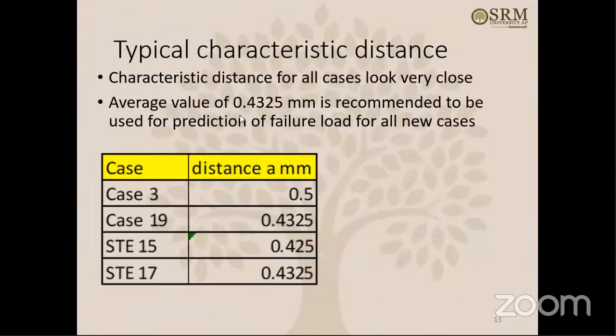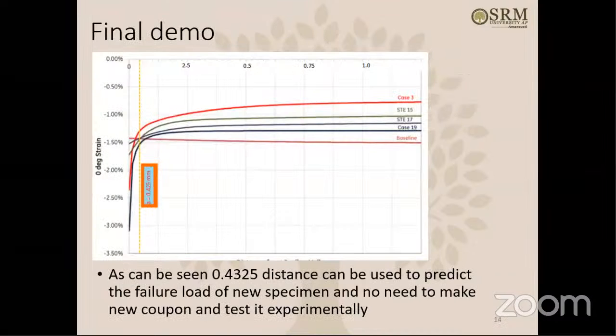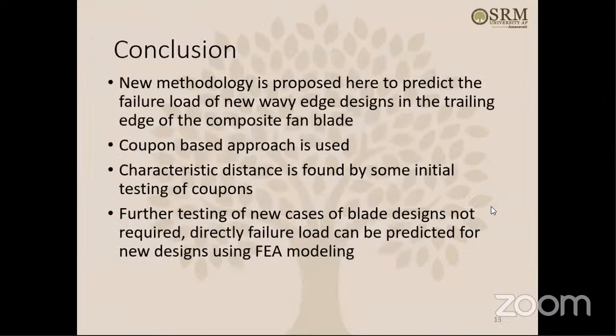Once we find this characteristic distance at which the strain variation meets the baseline level, that can be used to predict the failure load for new cases like this. As you can see, the 0.4325 distance can be used to predict the failure load of new specimens, and there is no need to make new coupons and test them experimentally. That is the basic purpose of this particular analysis.